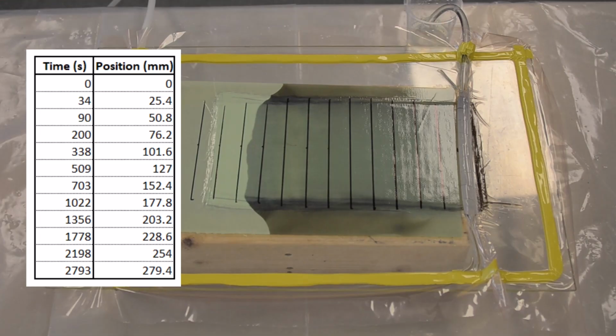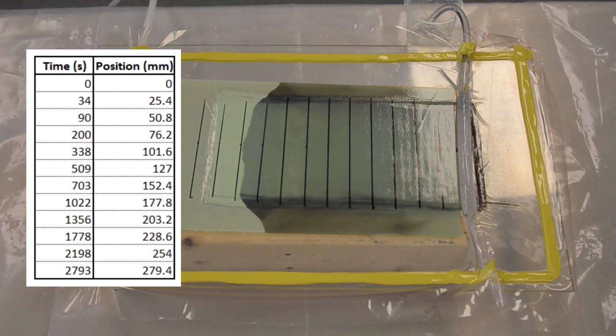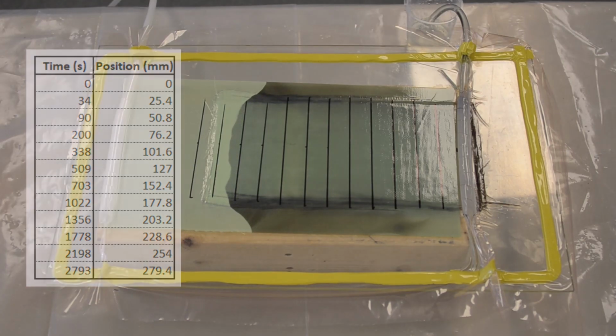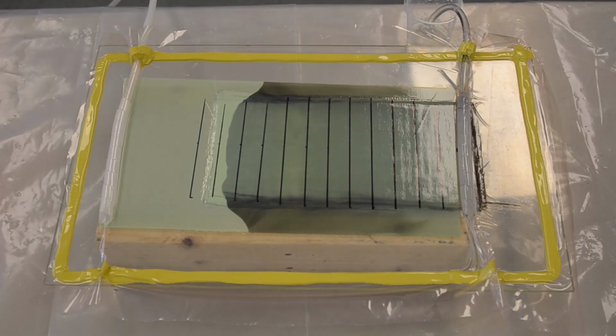As the infusion progresses, the resin flow front stays uniform, and one can tell that the flow rate has slowed considerably. This is exactly what we want to happen in our infusions. There are no signs of race tracking or other defects. Moreover, this allows the part to have a good fiber volume fraction. Overall, this infusion went smoothly.